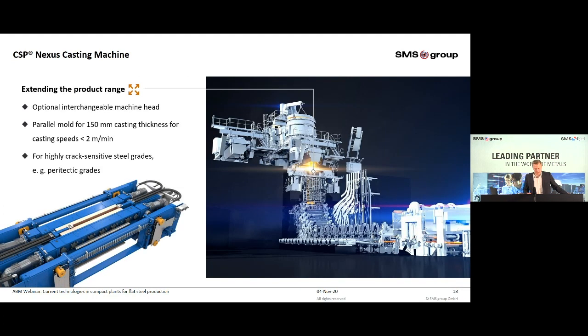The next slide shows an option to even extend the product range. For some highly crack-sensitive steel grades, it is required to cast at low casting speeds. Therefore, the machine head can be changed to use a parallel mold for 150 millimeter casting thickness to realize casting speeds below 2 meters per minute. This option enables the Nexus plant to produce steel grades with a carbon content in the peritectic region.